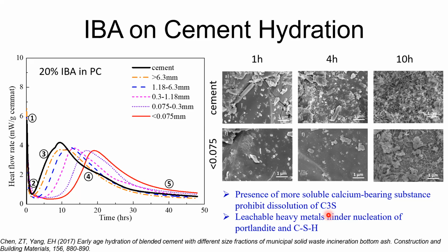Another potential mechanism is the high content of trace metals, the heavy metals in the smaller particles, that may hinder the nucleation of Portlandite and CSH. It's much like heavy metal poisoning to the cement. With this observation, we can say potentially IBA can be used as a retarder to delay or retard cement hydration.